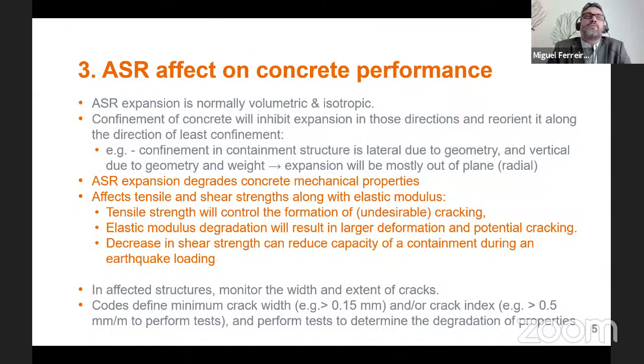So how does ASR affect? Well, the swelling or expansion of ASR, if the structure is unreinforced and if it's more or less evenly spread out, it's volumetric and isotropic. But this is not always the case. Often the concrete is reinforced, and the reactive aggregates are not necessarily uniformly distributed in the concrete. They might be in batches or in pockets. So this gives an anisotropic aspect to the expansion. And when confined, for example, with reinforcement, the expansion is usually redirected along the direction of least confinement. And mechanical properties of the concrete are affected by ASR, for example, tensile and shear strengths and elastic modulus. These are all affected by the occurrence of ASR in the concrete structures.